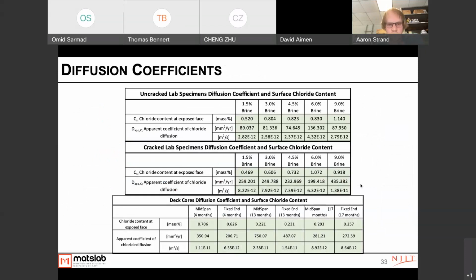These are the diffusion coefficients that we calculated from the data that we collected. And what's interesting to note is that we do see a fairly drastic increase in the diffusion coefficient for the cracked specimens compared to the uncracked specimens. And then also for the cores taken from the deck, we see a fairly high amount of chloride diffusion within the specimens that we tested.